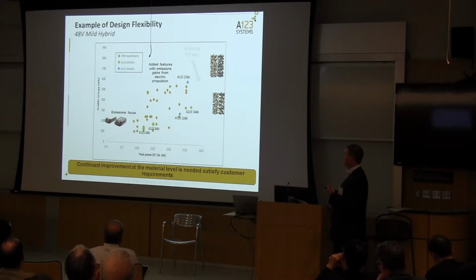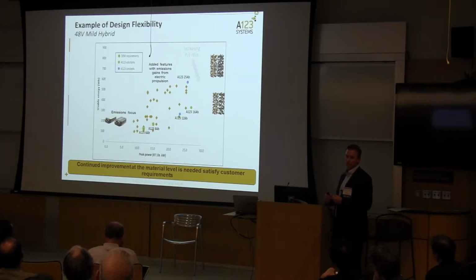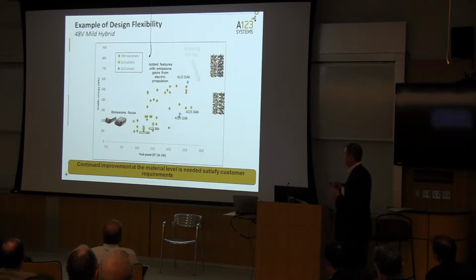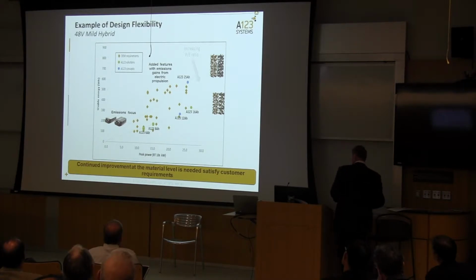And so what we're doing is, again, taking a fundamental approach to look at things like DCR growth to minimize that, looking at making higher thermal stability so you don't get calendar fade, so that at the end of life you really have very similar performance to beginning of life, so that we can meet these higher energy density values without degrading power. So again, this is kind of the first step in our journey with our Gen 4. And this has gained us about 50%. We have about 50% of the market in Europe and in China with this product.